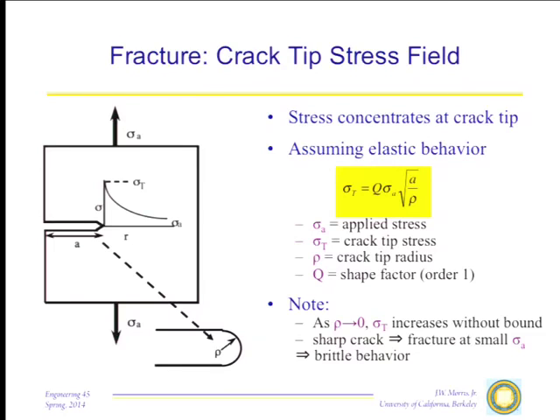Now look at the consequences of this. As rho goes to 0, the stress at the crack tip will increase without bounds. Of course, you can't do that because eventually it would exceed the yield strength of the material and get some deformation. But in theory, this thing goes without bounds. So if you have a sharp crack, then you can break this material, even at a relatively small value of the applied stress, because that applied stress gets ferociously amplified here at the crack tip, unless something like plastic deformation intervenes to blunt it out.